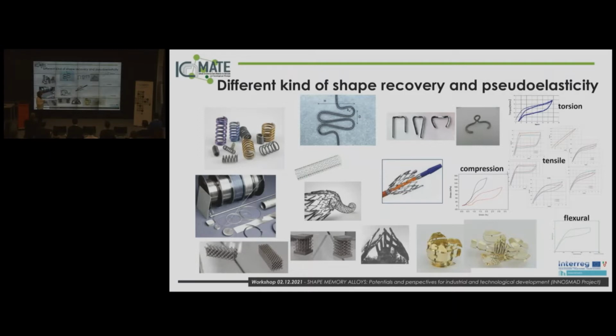The pseudoelastic effect can be used in all configurations: tensile, torsion, flexion, compression. In any case, we have the typical flag-shaped curves with different kinds of plateau, with different kinds of stress or strain, but this material can be used in any shape and in a lot of applications, starting from artistic applications. This is a sculpture, in jewelry or orthopedic devices and so on. We only have to consider which kind of driving force we prepare the material for. If we use the temperature, we have to use a small mass, small weight of the material. Or we can use the pseudoelastic effect. We can choose a very, very open possibility of shapes.